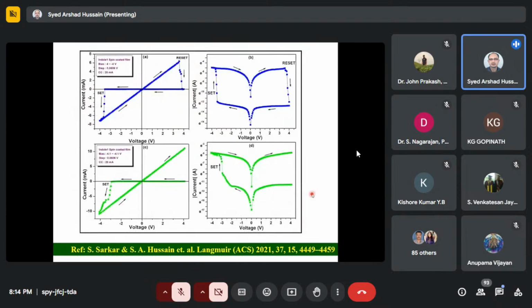Sorry. So here we have seen that our device showed bipolar resistive switching. Here you can see, it switches from the high resistance to the low resistance state. Then it retains the state, and again it's reset at a particular voltage and goes back from low resistance to high resistance. So it's possible in both ways. You can sweep, say, from 0 to minus V, then set here, then reset. Again, you apply 0 to minus V, reset here. Okay. Or the opposite polarity, 0 to plus V, it's set, then reset. So it's independent of bias polarity, we have found.